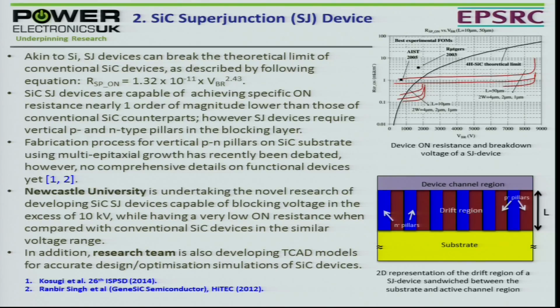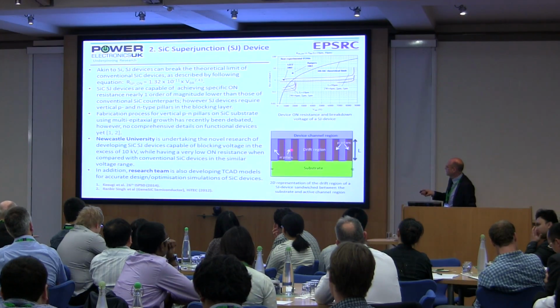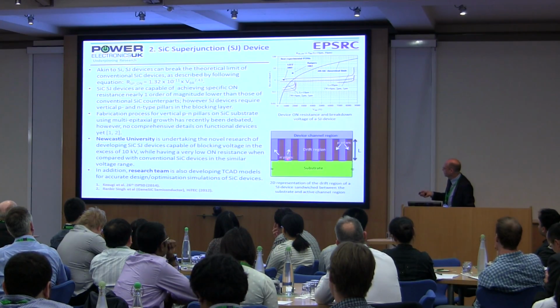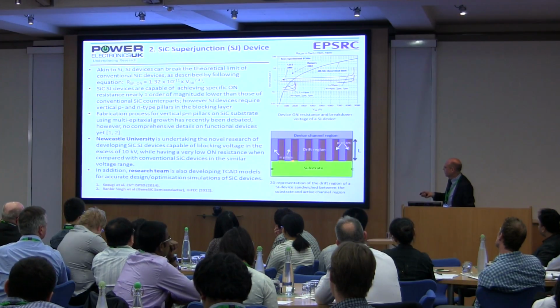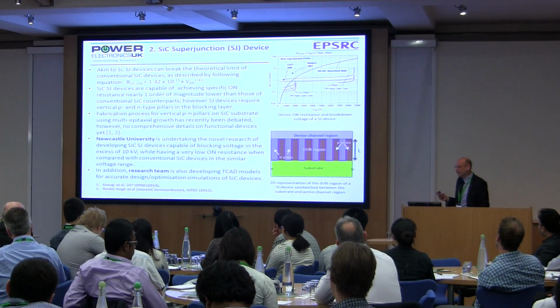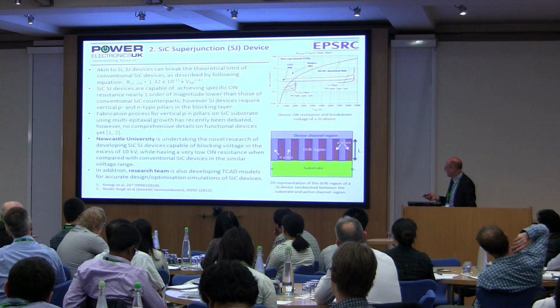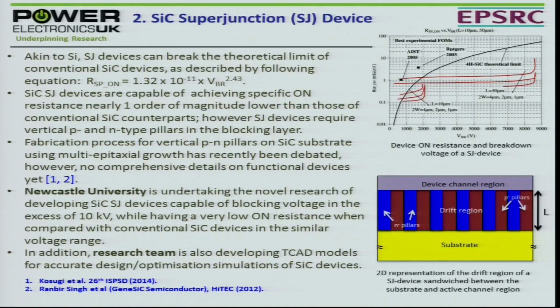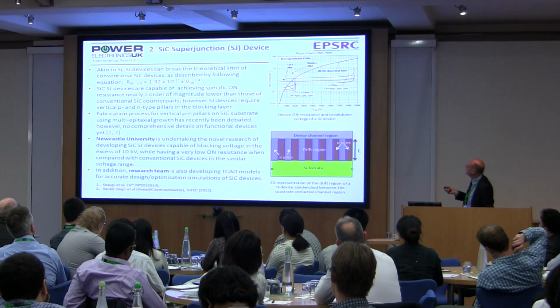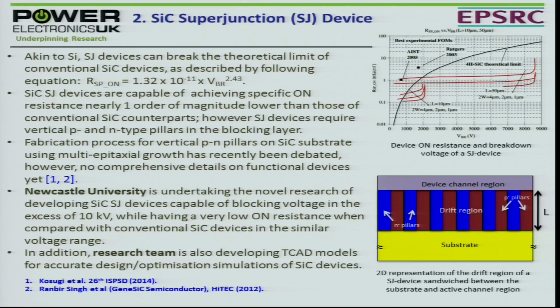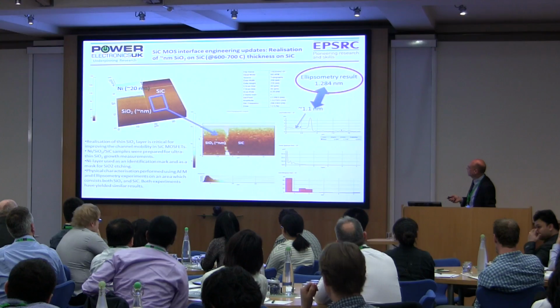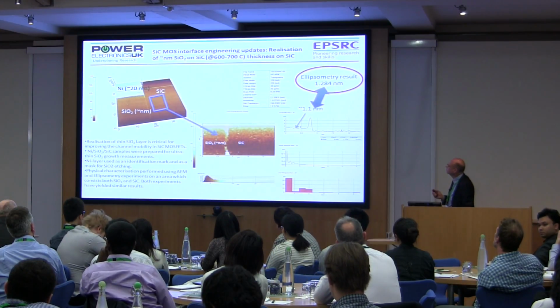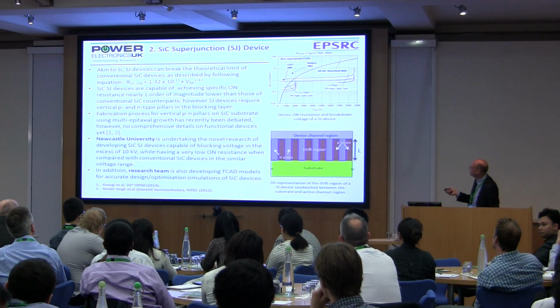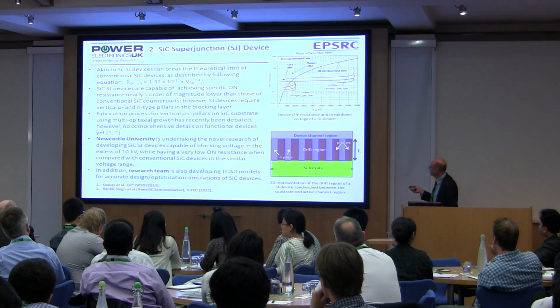This is difficult to do in silicon carbide, because the way they do this in silicon is with either lots of implantations to build up the P pillars, or they etch out a hole here and regrow epitaxy inside. Neither of those is really suitable for silicon carbide. So we're trying to look at what happens if we can build this structure using epitaxy. And there's some initial simulation results. Shows that you can get pretty much close or exceed the one-dimensional limit of silicon carbide by using these superjunction structures. And here's some more. So that piece of work is just started to make some devices. They've not actually got any results on that yet, but they will have in the next few months.